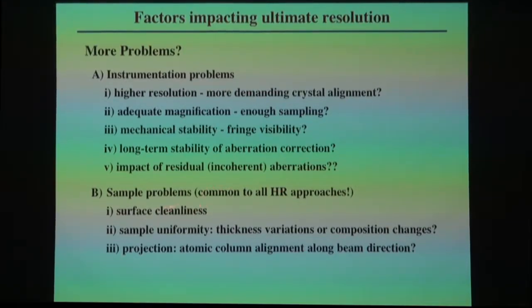And here are some other problems. Is your sample surface clean? Because if you're trying to get atomic resolution or sub-angstrom resolution, and you've got a little bit of junk on the top and bottom surface, a little bit of contamination, a little bit of oxide, in the case of a semiconductor, the surface cleanliness may be a problem to your ability to extract the highest resolution from your sample. This is becoming acknowledged more recently as a major problem. Is your sample uniform in projection? Are there variations in the thickness from place to place? Or maybe there might be changes in composition. And we are presuming that we have atomic columns being aligned along the beam direction. And if you're looking at defects, that may not be the case.